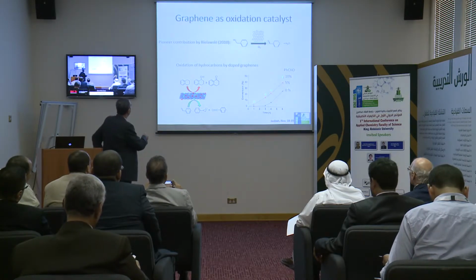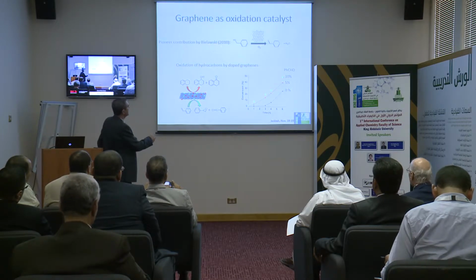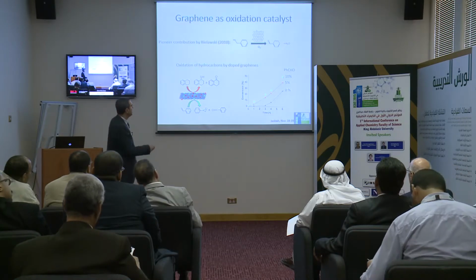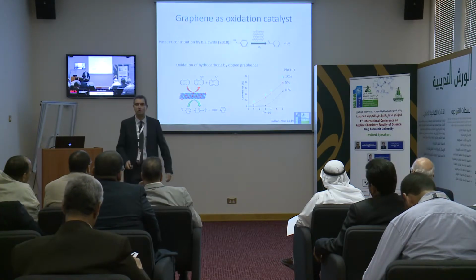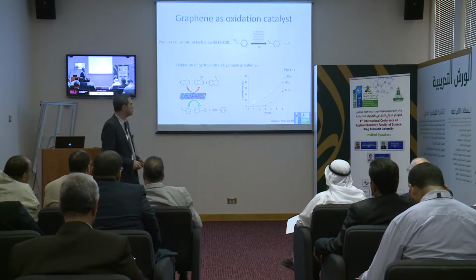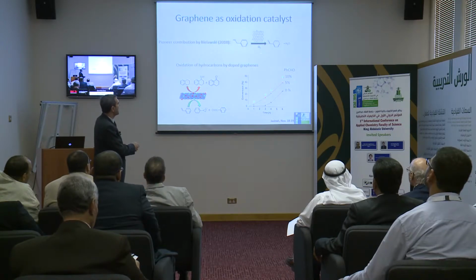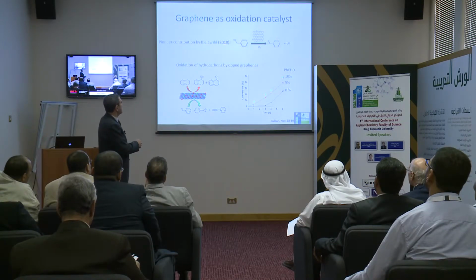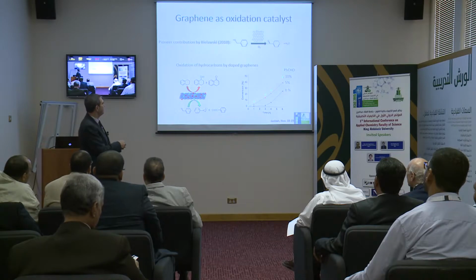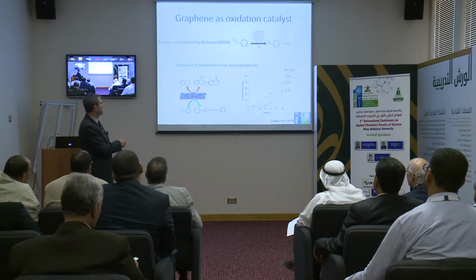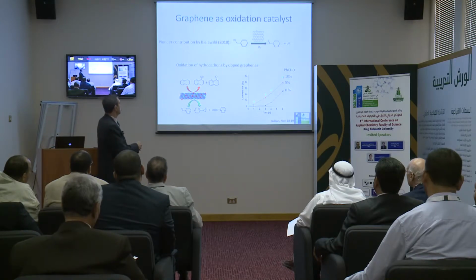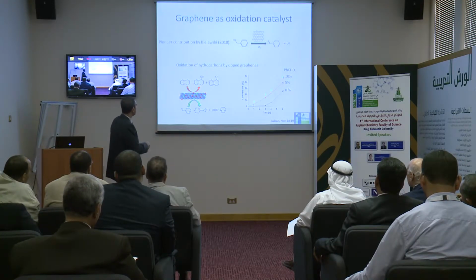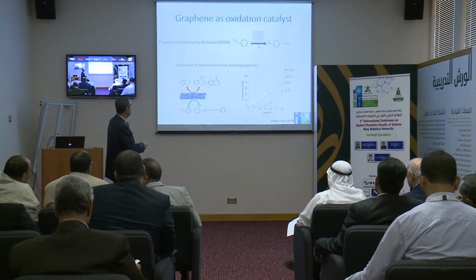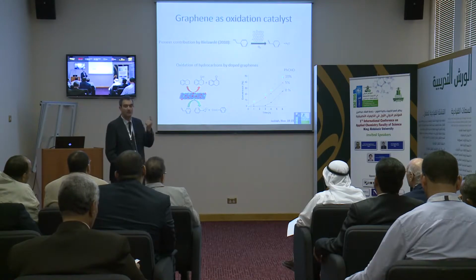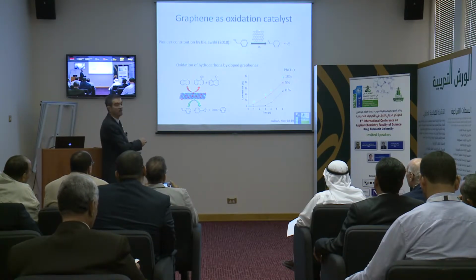So we follow the work by Bielawski in 2010, showing that graphene oxide is a good catalyst without any metal for performing the aerobic oxidation. This is very important because they are using just oxygen to promote oxidation. Using oxygen alone, you have an alcohol, and at the end you produce benzaldehyde. But in this original paper from Bielawski, they were using graphene oxide in a very large amount. Typically, it was 50% weight of graphene oxide and 100% weight of the alcohol. So by using our doped graphenes, we were able to reduce the amount of graphene. Actually, we were working with 1 weight percent, only 1 weight percent, while here it was 50 weight percent.